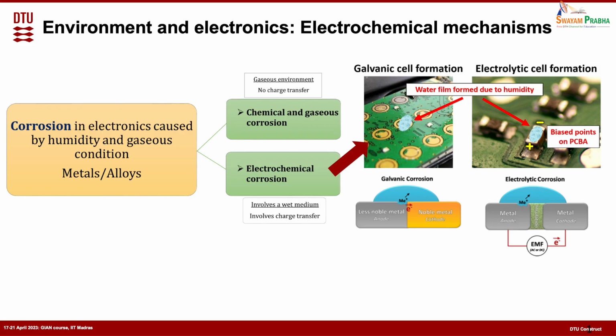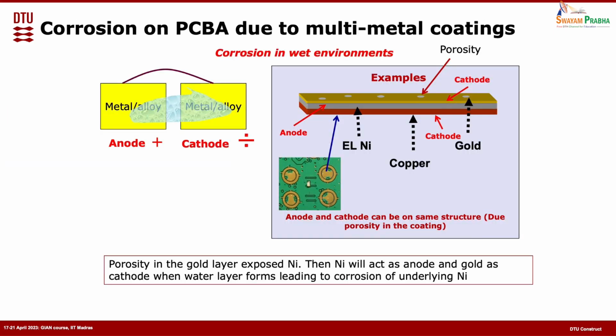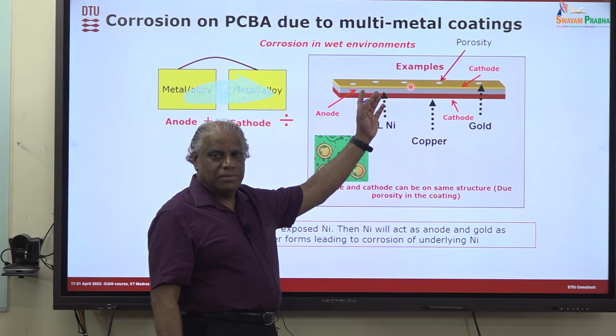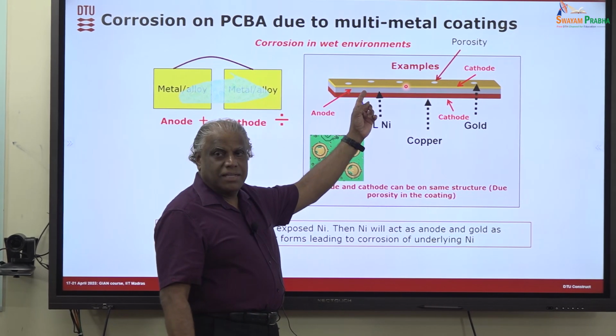Just to elaborate a little bit on that, this galvanic corrosion problem is with gold. You have the porous gold layer, electroless nickel below that, and then the copper. If the gold layer is porous, when the water film forms and connects, the electroless nickel will corrode and the gold will peel off, and then you have all the electrical connection problems. Why do they put this electroless nickel below the gold?